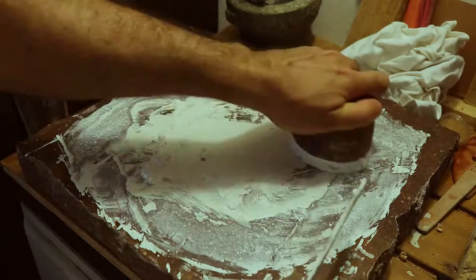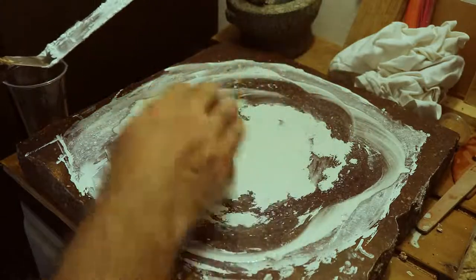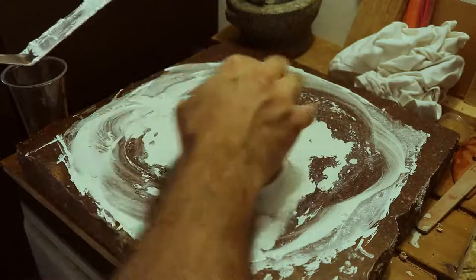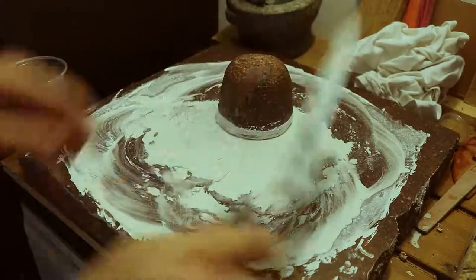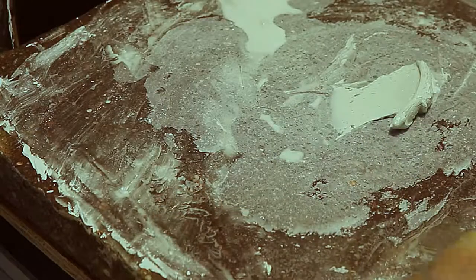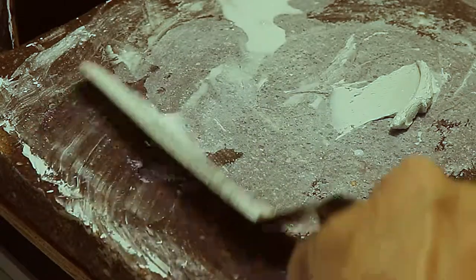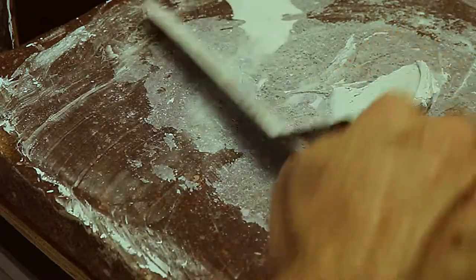Of the safety concerns. Now this is important. You'll see that the oil and the pigment will start joining together, and the water will actually get expelled from the mixture. This is exactly how it's described by Felipe Nunez in his treatise. There you see the lead white being separated from the water. The reason is that you get a lead soap and the water doesn't want to be there. So you get a combination of the linseed oil with the lead white, and it's a very safe way to prepare the lead white without having to handle it in powder form.